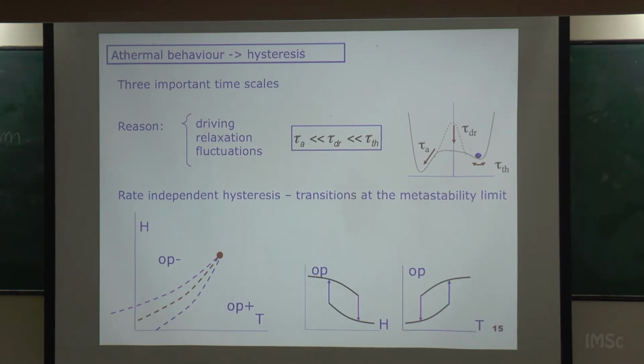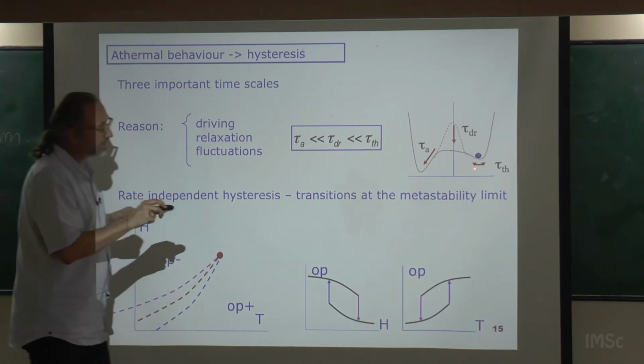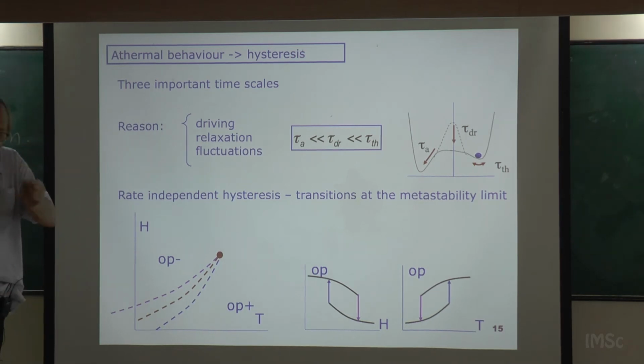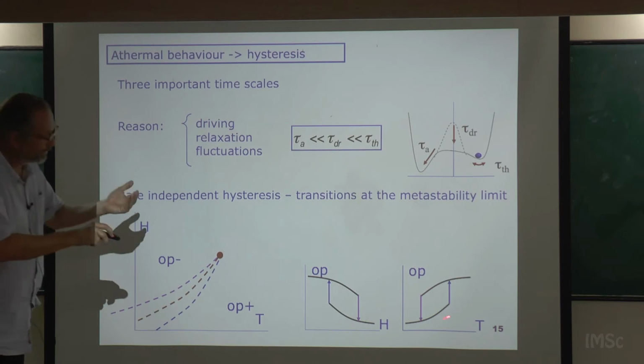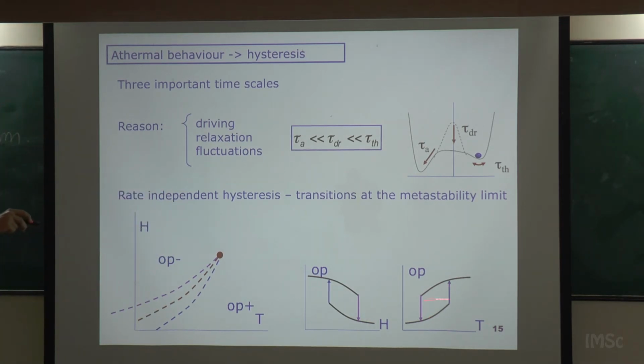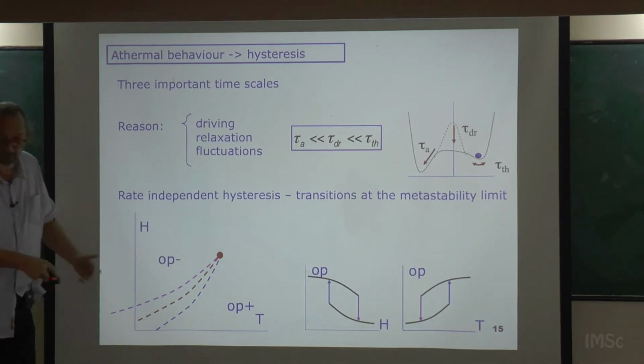So it's what I am plotting here. The system waits until the barrier disappears, and then only in that case it relaxes towards the new minima. And instead of having one jump, you have two jumps. Instead of jumping here, where that would be the equilibrium, you have to cool more, or you have to decrease more the field, depending on how you are driving, or you have to increase more the field, or heat more, in order for the transition to occur. Okay, so that is the explanation of the hysteresis, and this explains why in the phase diagram, instead of having only one line, I have two metastability lines.